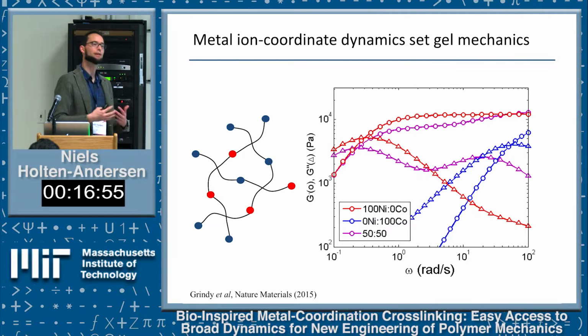So it's sort of a built-in stiffening mechanism: if you deform the material fast enough, the network that operates on these timescales kicks in and the material gets stiffer. So the faster you pull, the stiffer the material becomes, and you can engineer that very controllably with these types of metal ions.